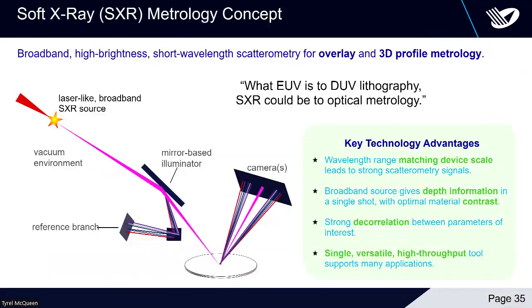So the idea for soft X-ray metrology is basically like a diffraction-based overlay. You deal with several gratings that are lined on top of each other, but now you do that with nanometer pitches. So you need to generate soft X-ray lights, reflect that onto your metrology target, detect all the diffraction orders, and then you get your overlay and critical dimension measurements. Sounds easy, right?